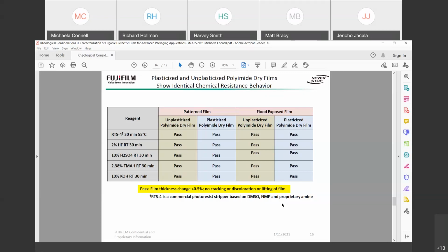These were done for 30 minutes at room temperature, besides the RTS4, which was done for 30 minutes at 55 degrees Celsius. In this case, we defined passing by a film thickness change of less than 0.5% and no cracking, discoloration, or lifting of the films. By this criteria, both films passed when both patterned and flood exposed, showing that the plasticizer had no effect on the chemical resistance of the film.